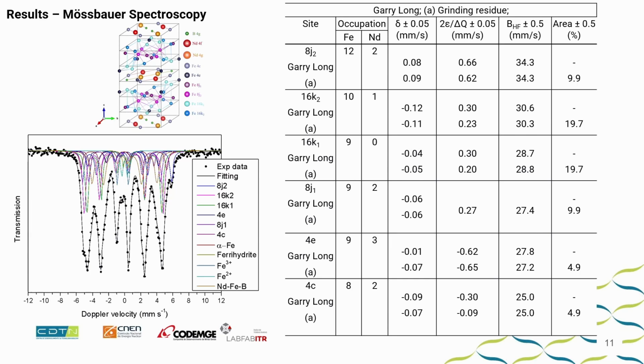we find this alpha iron in this powder, this sludge, and also we find another ferrihydrite phase. When you cut, or with some literature, you find always with this friction of this machine, of this diamond saw cut or alumina polish, we produce some pressure or friction, and this other phase here is this kind of distortion in this lattice parameter, and we find a better fit with this simulated Mössbauer spectra.